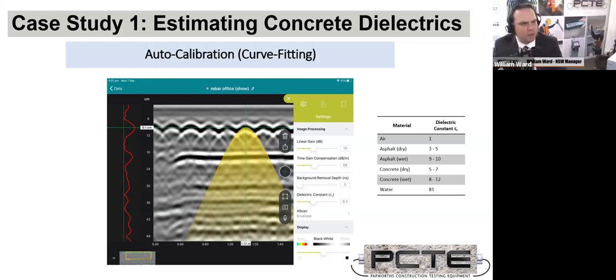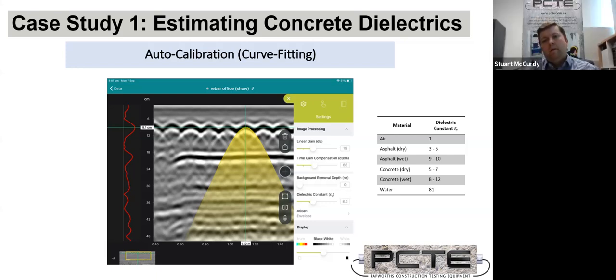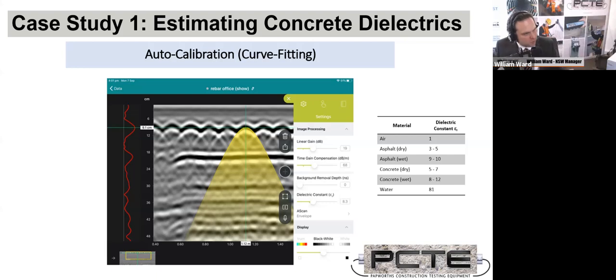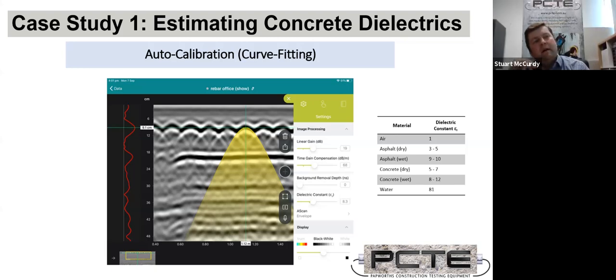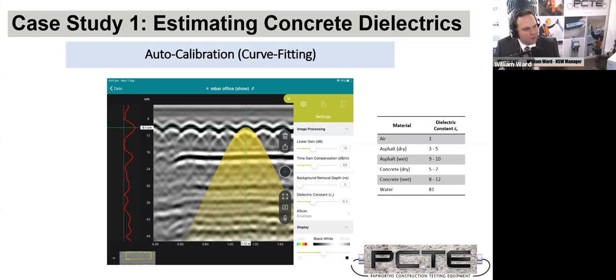Now, Stu, just a few questions from the chat. The first question was, we see a parabola when we cross a reinforcing bar perpendicular. What will we see if the rebar is parallel to the GPR's movement direction? Oh, in that case, you'd be running over top of the bar. So the distance the GPR would travel to hit it would always be the same. So you'd get a straight line. The second question was about taking the depth measurements from the black band.